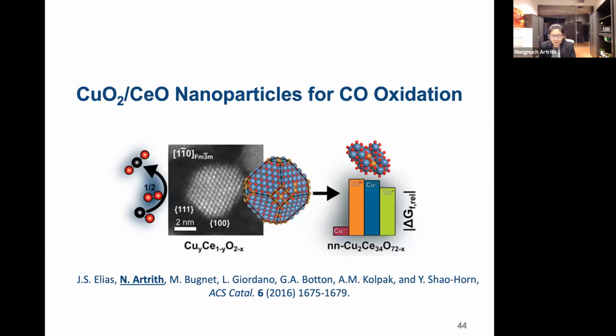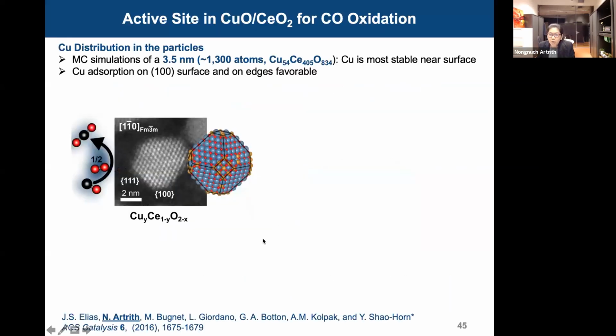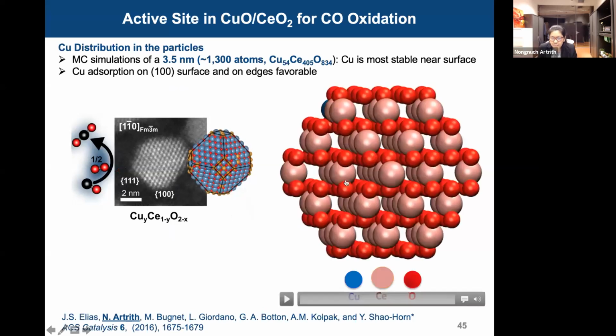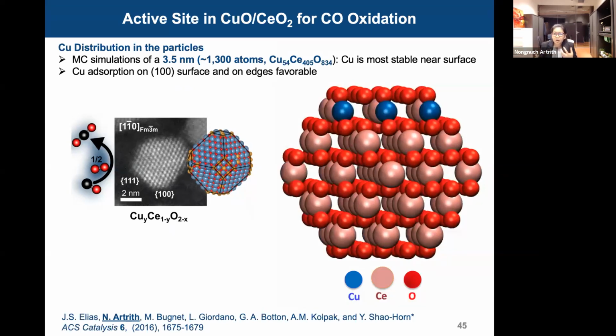Another example, again together with Professor Yang Shao-Horn. One of the students, now Dr. Elias, just came and said, can you please help me to find where the copper atom sits in the ceria oxide nanoparticle here? Because in the experiment that we see in this image, everything is only gray and white and black. I don't know where the copper sits. So we just performed neural potentials and used them again in Monte Carlo simulations for the cluster size around 3.5 nanometer nanoparticles with around 1,300 atoms to understand where the copper atoms really insert and sit in the ceria oxide here.